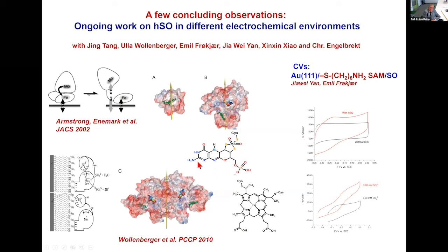This is the molybdenum center, this is the iron center, a heme group, and the common view is that the molybdenum domain is attached to a surface, a positively charged surface, and then with the iron domain swinging in and out, with a certain probability it will get attached to the molybdenum, and the catalytic process can be fulfilled. These are charge distributions that have led to models such as this one.